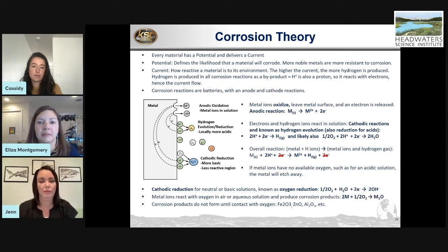Something interesting I want to explain, though, is that people always say corrosion needs oxygen. But what does that really mean? How does corrosion need oxygen if you have this acid environment? Where's your oxygen here? Well, acid is not actually corrosion, technically it's oxidizing. When you're looking at the reaction with the acid, it's just etching it. It's not good, but you're getting this driving reaction the whole time. You're getting hydrogen bubbles, the iron and the metal is going off into the solution, but you're not having any corrosion product.